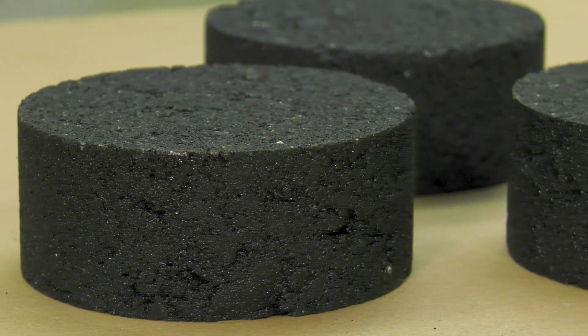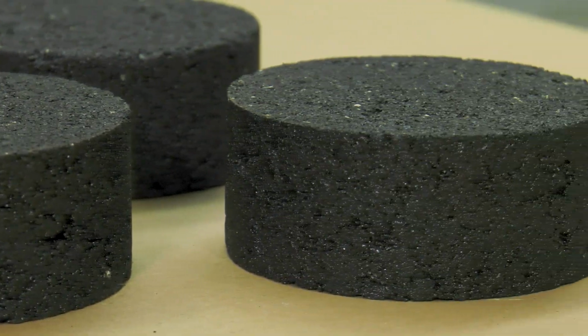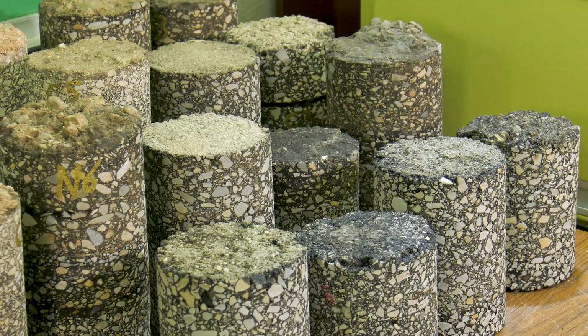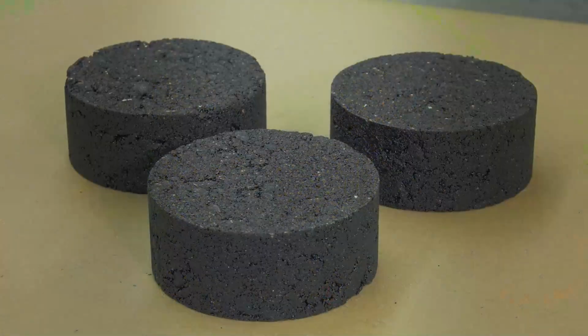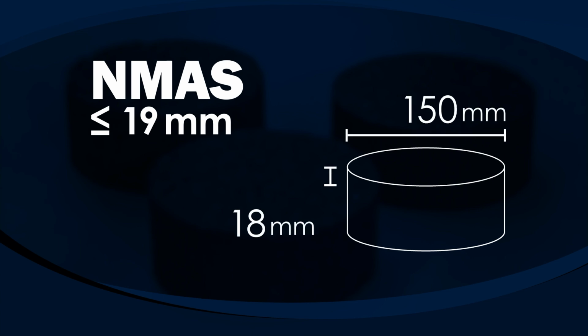The ITCT test can be performed on laboratory-prepared test specimens or cores taken from the field. For the mixtures with an end mass of 19 mm or smaller, the specimens should be 150 mm in diameter by 62 mm thick. For the mixtures with an end mass of 25 mm or larger, specimens should be 150 mm in diameter by 95 mm thick.